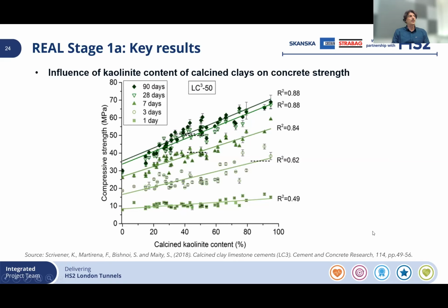So although we initially were a little bit concerned with the results we got, we examined the literature and we're very encouraged, let's say, to find something. For example, in this graph, for 20% kaolinite content, that's on the x-axis, in the LC3 formation, which is a combination of calcined clay, limestone, and Portland cement, strengths of up to 40 megapascal could have been achieved. So we thought that this could be a good starting place for us to try and produce cementitious mixes with calcined London clay.